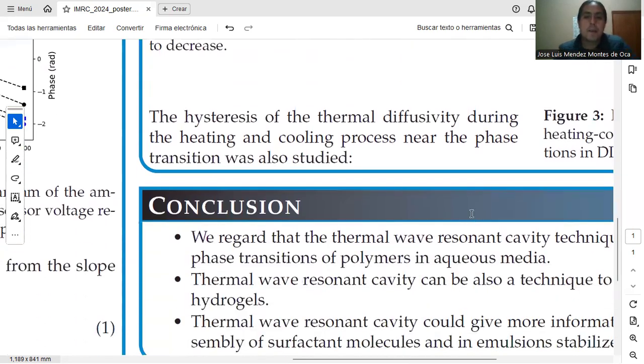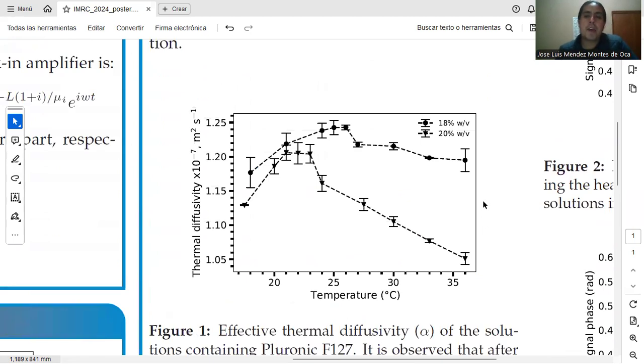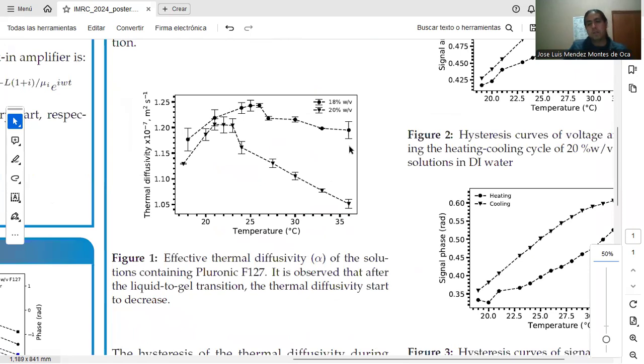As conclusions, we observed that this technique was able to detect differences in the concentration of pluronic, and was also able to detect differences upon temperature in the thermal diffusivity. And it was possible also to observe the transition from this point of view of the thermal diffusivity. We regard that this is another way to observe it. Usually this transition is observed with the viscosity of the material or with calorimetry, but this is another way to observe the transition.